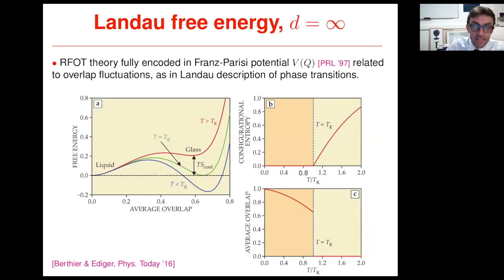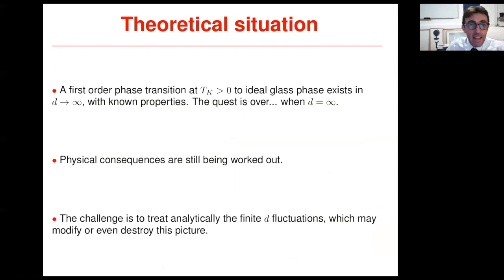So in a sense, the situation is very clear at the mean field level. We have this first order phase transition, which occurs at a finite Kauzmann temperature to an ideal glass phase that exists in this mean field limit. And the transition and the glass phase have known properties. So in a sense, the quest that I mentioned in my title, the quest of an ideal glass, it's over, but it's over only in the mean field limit. For instance, in the limit of a large number of space dimensions.